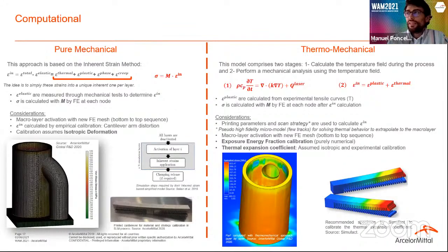And now I present here an overview of both models that we used for predicting the residual stresses. So the first one is a model based on the inherent strain method, which is a purely mechanical model. Here in this model, we input the elastic strains and the response of the material, and we calibrate the inherent stresses experimentally by cantilevers, and with all that, the model calculates the inherent strain, and the idea is that they simplify all these strains to a unique inherent strain per layer.